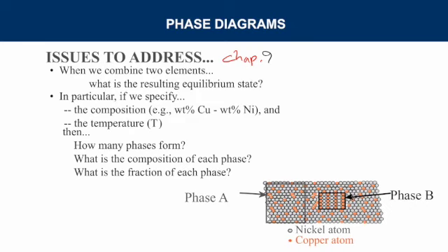So it's similar to what we've talked about before. If you're putting sugar into water, if you do that at room temperature, a lot of the sugar will drop to the bottom of the volume that you've created. But if you heat it up, you can dissolve more of the sugar. Same thing with metals. If we put in impurities like copper and nickel, we can increase the tendency for copper and nickel to interact by variations in temperature. Then obviously the ending result is if we heat it high enough, we'll melt it. So phase diagrams show us the melting points, the liquid phase, the solid phase, and the solid phases if things precipitate out into various regions.